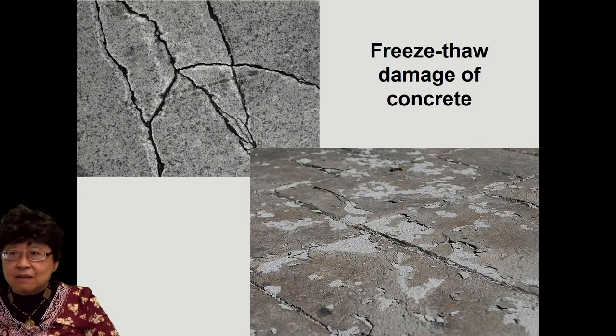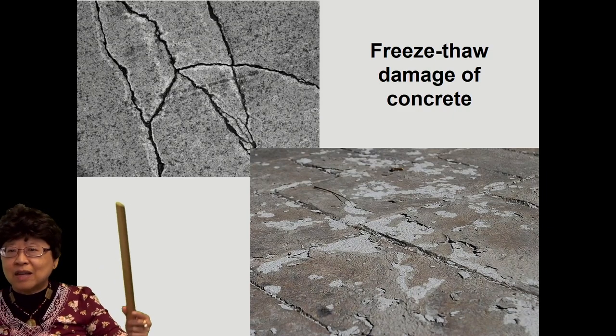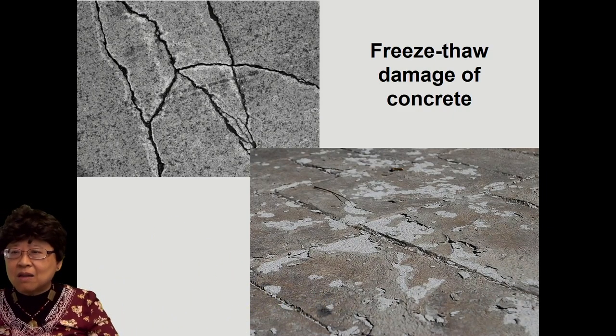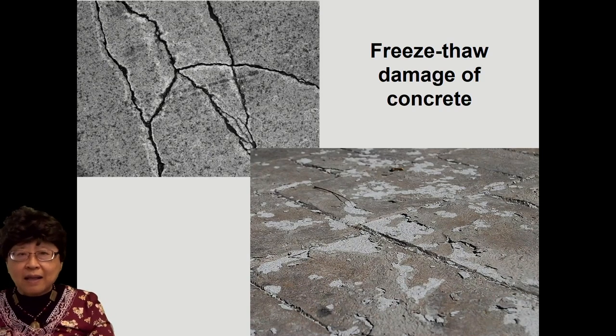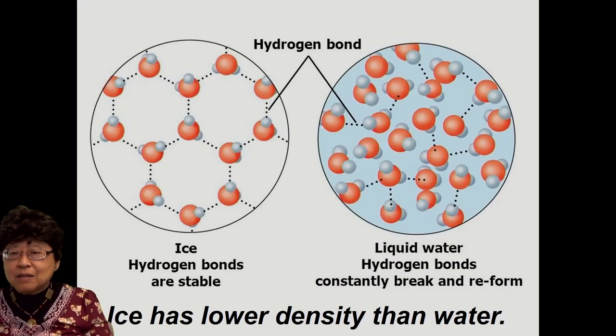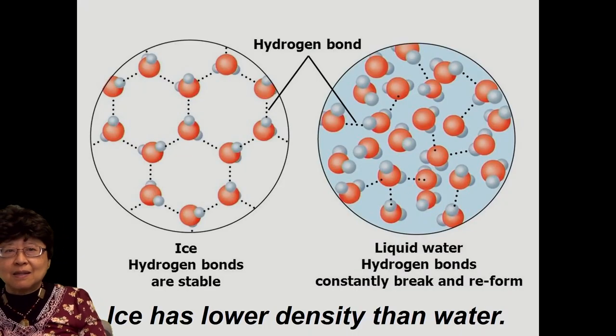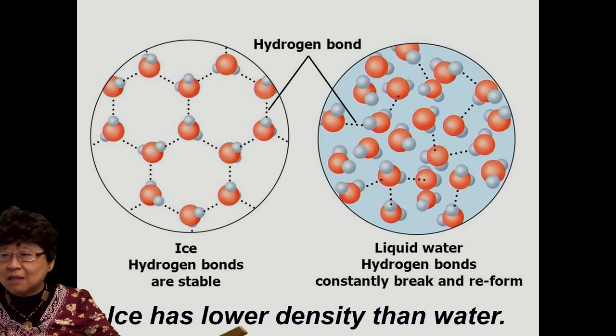One of the reasons for the damage of the concrete is due to freezing and thawing. Okay? And you get cracks because of the multiple cycles of freezing and thawing that the concrete experiences. The reason why freezing and thawing is such a headache is that ice has lower density than water.